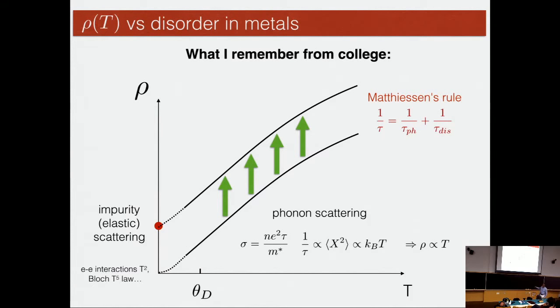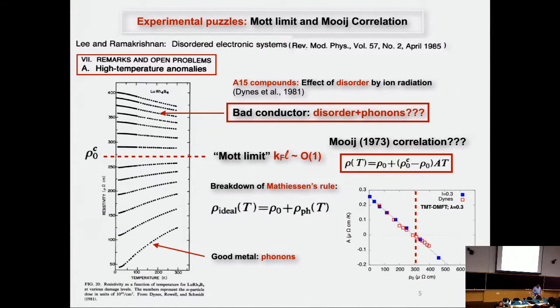And that will tell you that in addition to making the resistivity finite at low temperature, this whole curve will be shifted up like this. And this is indeed observed at weak disorder within the Drude regime in many metals. And this is an accepted view of what happens in metals around the room temperature regime. I'm not talking about the super low temperatures where there are some higher order weak localization terms. But if you actually look at the literature and ask, well, what happens when you make